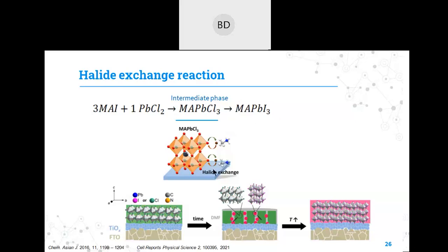So when you anneal it for a longer time at 90 to 100 degrees centigrade, what happens is the chloride starts going out from the crystal structure and iodine starts replacing the chloride. And finally, there will be a MAPbI3 structure at the end of the complete crystallization process. So here the complete process is governed through the intermediate phase, and this intermediate phase is one of the reasons for the large grains in this perovskite formation.